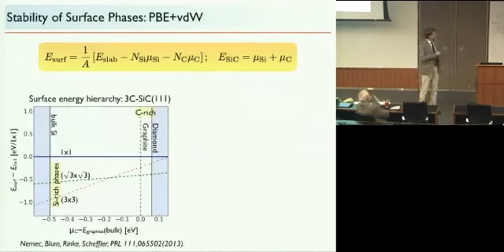And I'm drawing the results here in a so-called surface phase diagram as a function of the carbon chemical potential on the x-axis. What you see here is the surface energies, and at a given chemical potential, the stable phase is the one with the lowest energy. You see that there are these 3 by 3 and square root 3 by square root 3 phases, which I mentioned before. They're not yet graphene. This one is the lowest energy stable phase in this range. This one is here. And then we come to the carbon-rich limit around graphite.